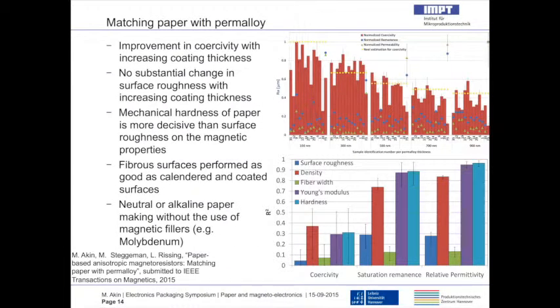So I come to the second part of the presentation, where I talk about the efforts we put into finding which paper is made for this application, basically the anisotropic magneto-resistance on paper, or soft magnetic coatings on paper. The goal we set up is a coating that has the lowest coercivity, basically the lowest magnetic force you need to magnetize and demagnetize. This is an indication of how sensitive your material is, but also how well this magnetic coating on paper can retain the magnetization within itself, that's the remnants, and for sure large permeability.